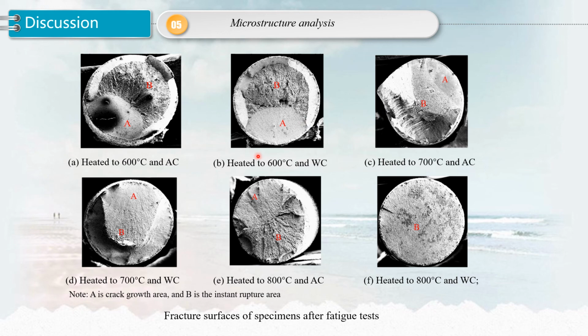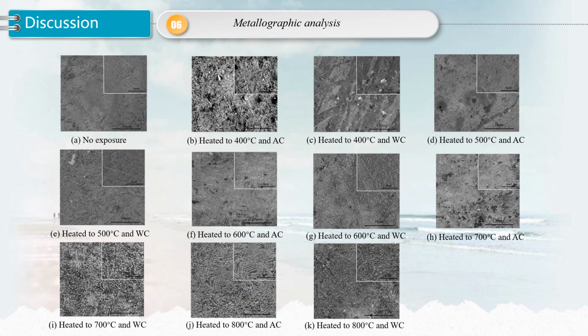The second is the instant rupture area, as shown in picture B, where the specimen fails instantly. It is somewhat rough with some radial fiber and shear lips. Moreover, metallographic analysis was conducted. It is seen that the microstructure gradually changes during the heat and cool process. This is the root cause of the change in mechanical properties.